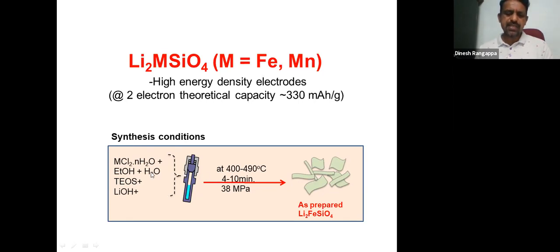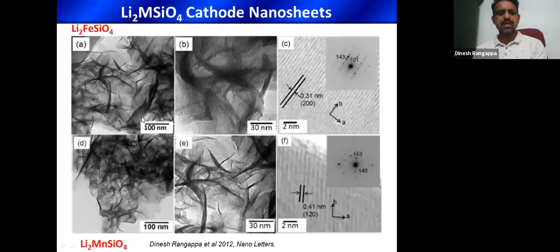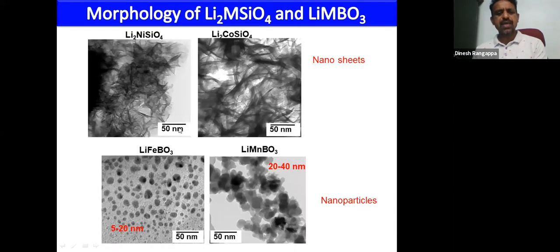Here you can see a similar synthesis condition, where metal salts are in an ethanol and water mixture. We synthesize this material at 400 to 490 degrees centigrade within 4 to 10 minutes at 38 megapascal. We could get lithium 2 iron silicate and lithium 2 manganese silicate material. Here you can see lithium 2 iron silicate in a two-dimensional nanosheet structure, and similarly lithium manganese silicate also has a two-dimensional nanosheet structure. Similarly, we could make lithium nickel silicate, lithium cobalt silicate, and some other materials.